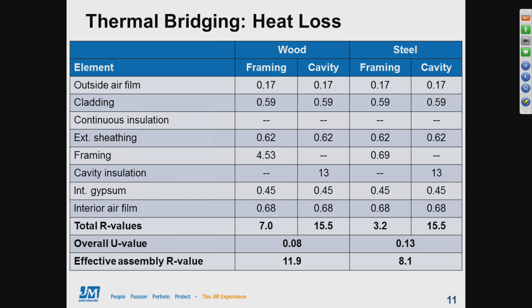So for each wall area, for each section, we simply add up those R values that the layers provide. And then for the overall performance, first we have to convert those R values to a U value, which is called thermal transmittance. U value basically equals 1 over the R value, and vice versa. We first convert to the U values at this step because this lets us account for the fact that the heat going through this wall will actively look for and take the path of least resistance. So once we've done our area-weighted average as U value, then we can calculate an overall effective R value, which makes it easier to really see what the impact is of the thermal bridging.